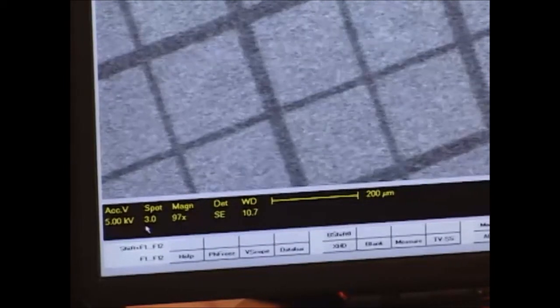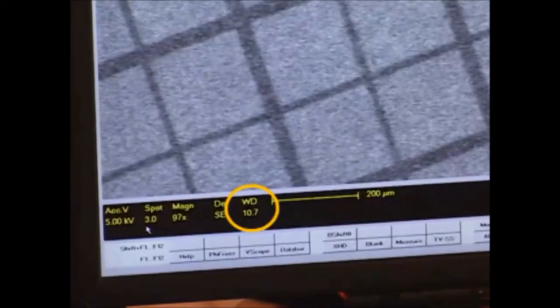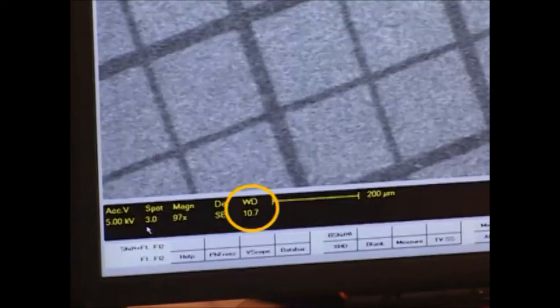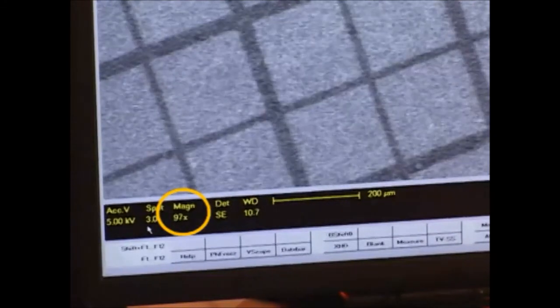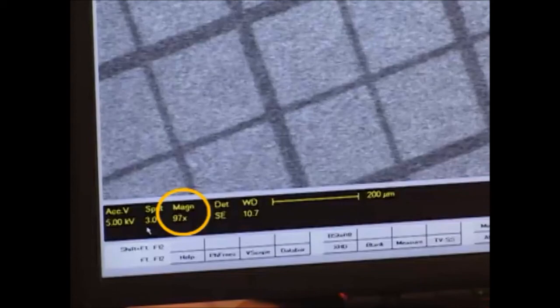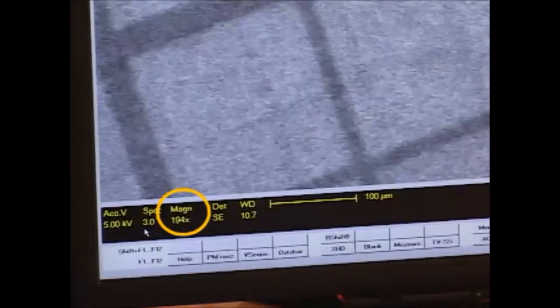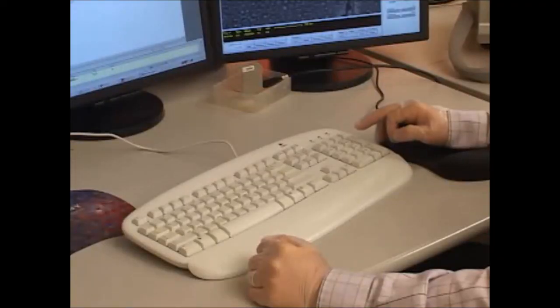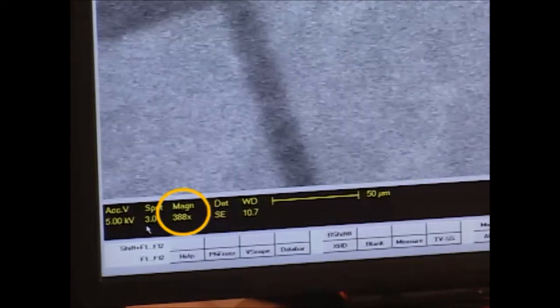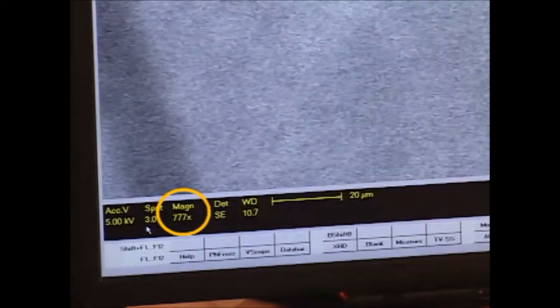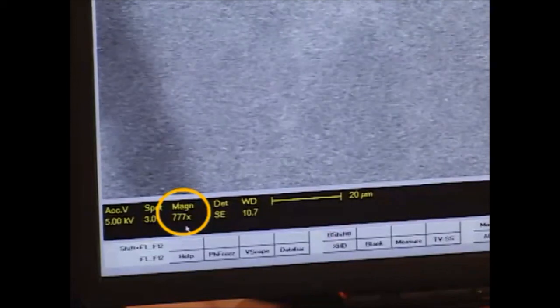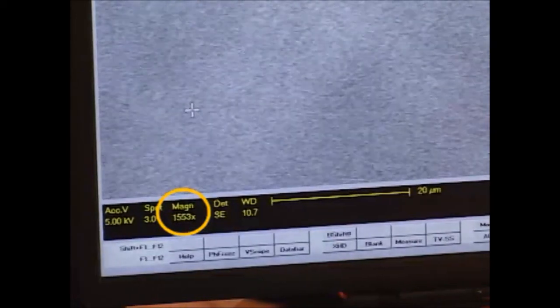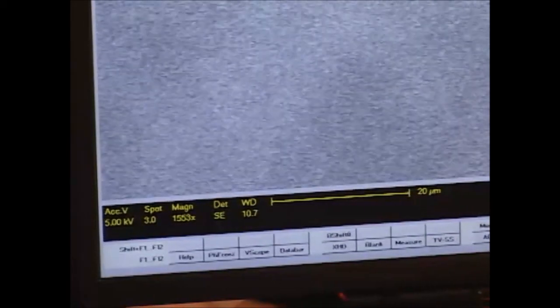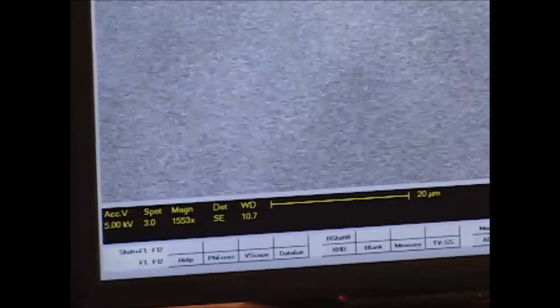Now the sample is much more in focus than it was, and you see the working distance reads 10.7 millimeters, but the magnification is only 97x. I need to get it in focus at 2000 or greater. So I'm going to zoom in by hitting the plus button on the number pad. That doubles my magnification each time I push it. 776, 1553. I'm going to stop and focus because it's clearly blurry right now.